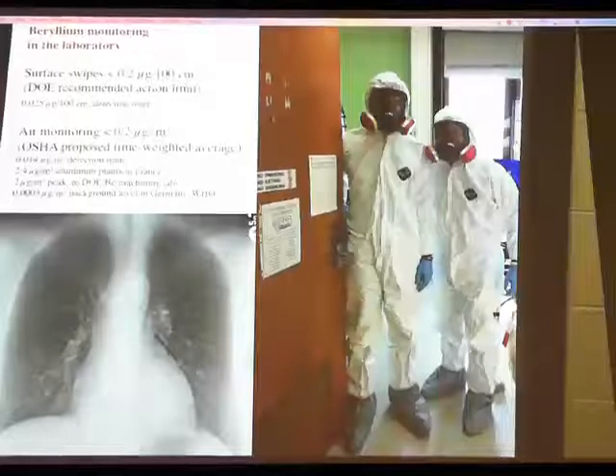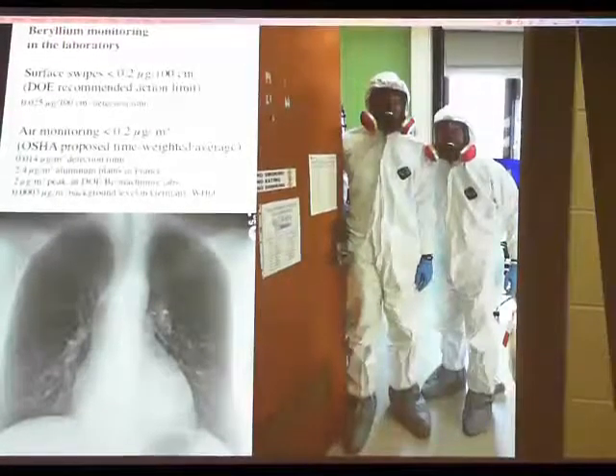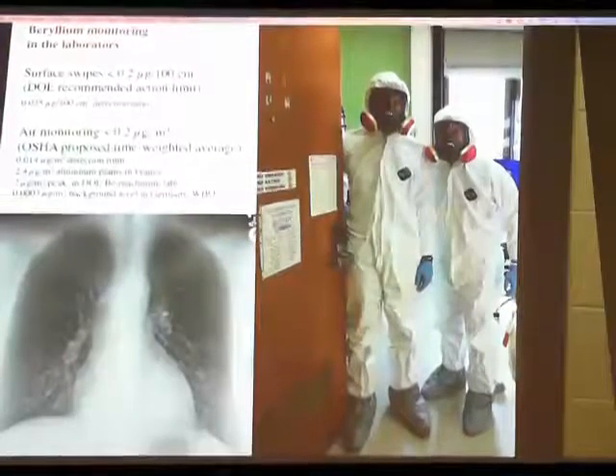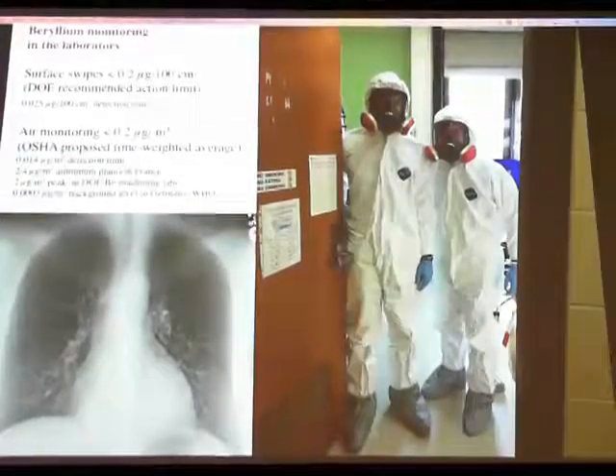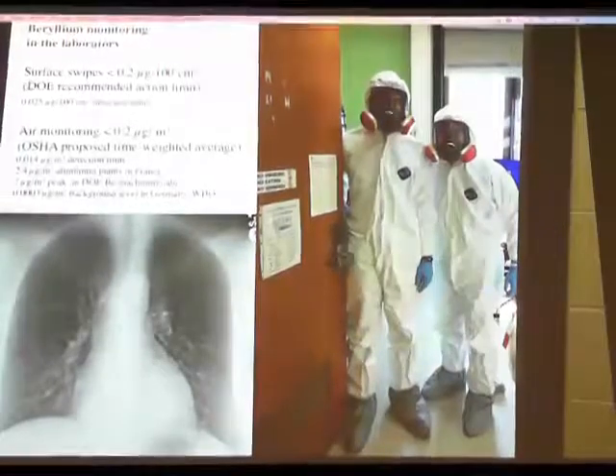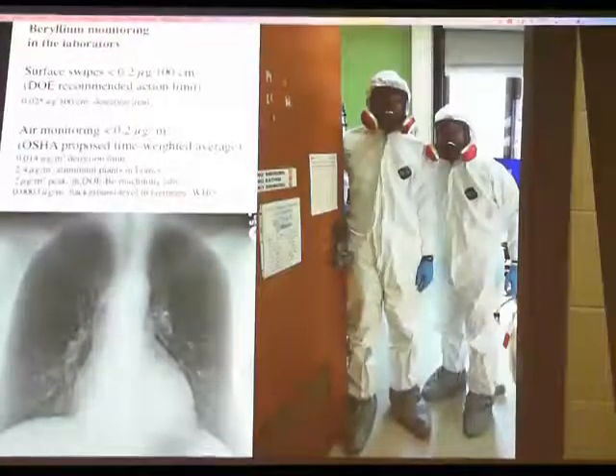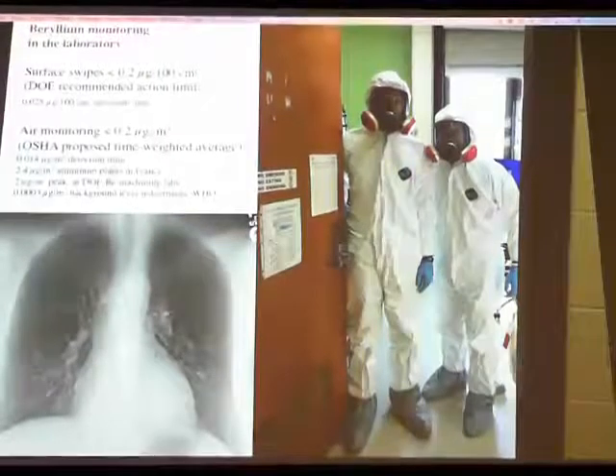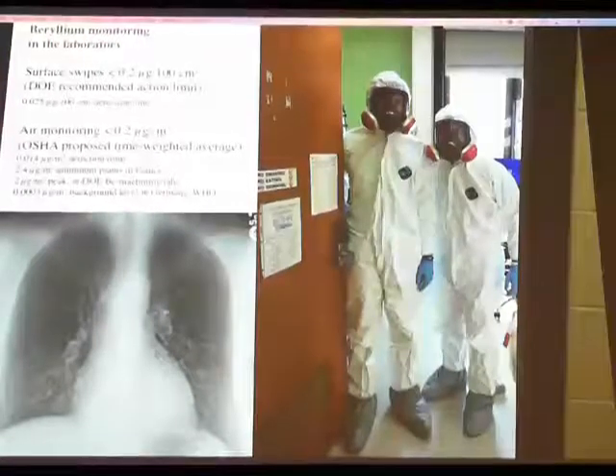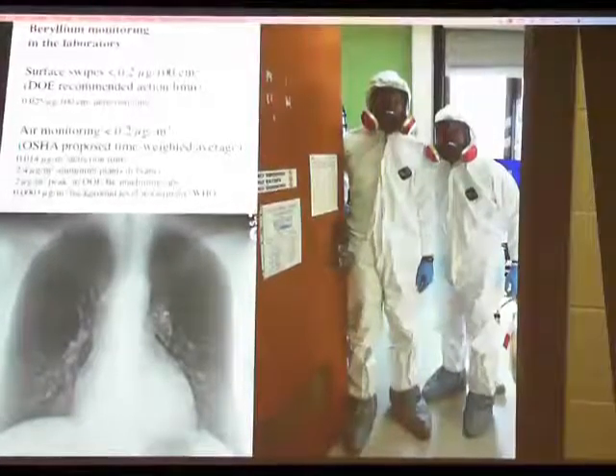Then we work with beryllium, and so we take beryllium safety very seriously. So all of the beryllium that we work with is contained in glove boxes, and our labs are not beryllium contaminated, but we do monitor the labs for beryllium contamination, and anytime we do cleaning, we suit up just in case there's hotspots of beryllium that we haven't detected. So we do periodic house cleaning where we suit up and we scrub the floors. And then anytime we open the glove box or do any retrofits to the glove box, then we suit up. So we do surface wipes and air monitoring. And we aim for 0.2 microgram per 100 centimeter square for surface swipes, which is the DOE recommended action limit.